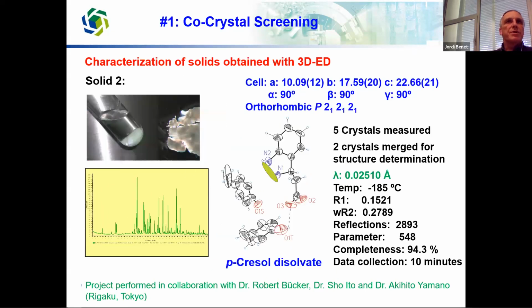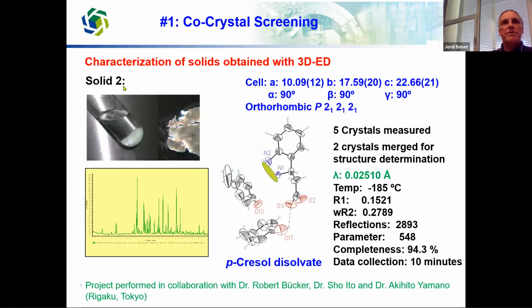In the second step, we did a second measurement of another solid. There's a mistake. This should be solid 4, I think, and then we got another structure. In this case, this API was forming a solvate, so you have 2 molecules of paracresol in the crystal. In this case, we needed to measure 5 crystals. We measured 2 crystals and got this data set with a completeness of, let's say, 94.3%. As you can see, error values of 15% are quite normal. This is a good error value in my opinion, so you need to get used to these values.